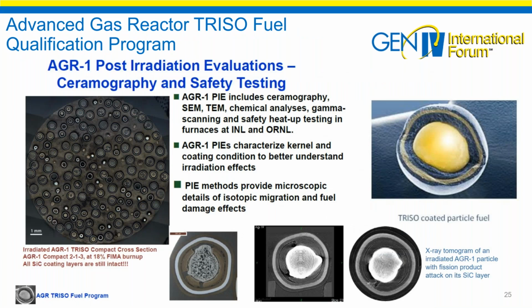It's not good enough just to irradiate the fuel and say, you didn't emit any fission products. You've got to look at what's happening. So in our PIEs, we use ceramography and safety testing, advanced SEM and TEM, chemical analyses. We gamma scan not only our compacts and the test train, we also look for the needle in the haystack. Each compact had about 3,000 particles per compact, and to find the ones that could have failed, we have to basically deconsolidate and search for them. We've developed different methods to do this.